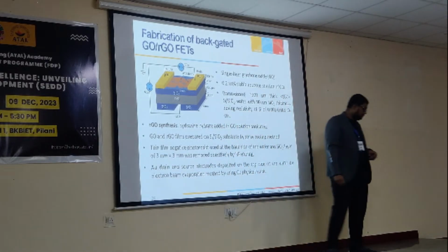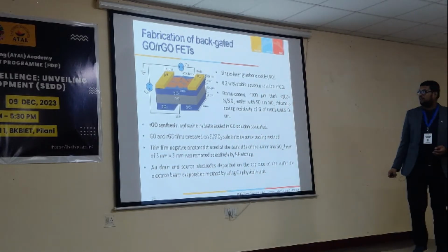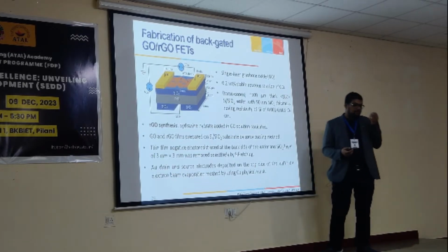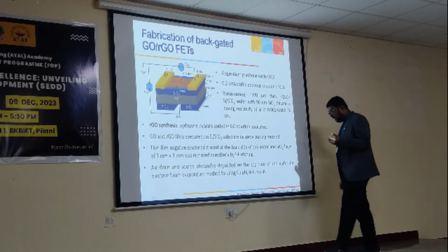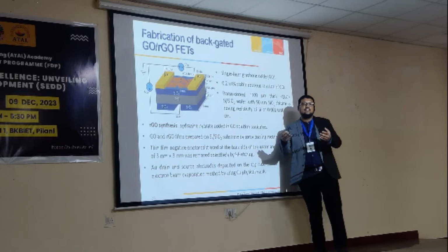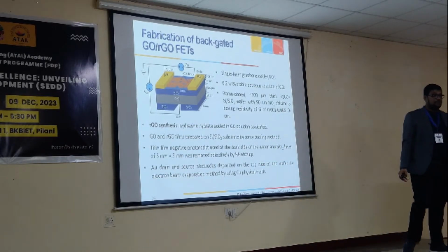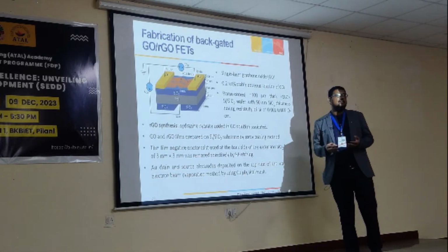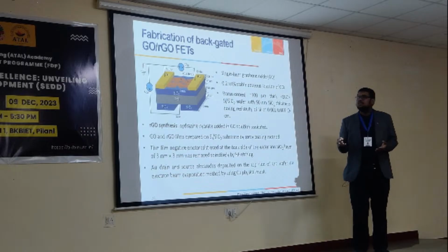Initially this graphene oxide shows p-type behavior, p-type semiconductor. Why is this a p-type semiconductor? 2D materials have very low carrier concentrations. Carrier concentrations are normally considered in per centimeter square form. Normally in silicon, moderate doping is 10 to the power 16 per centimeter cube. But here we represent it in the order of 10 to the power 12 per centimeter square, per unit area, because charges are available in a 2D sheet. They are very limited in number.